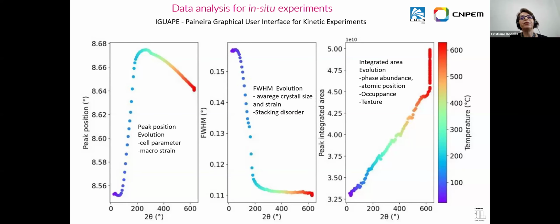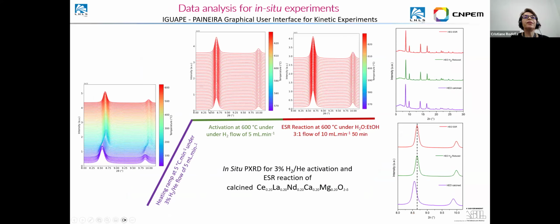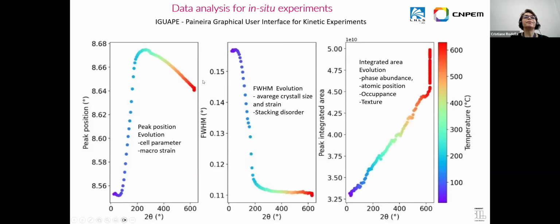What else do we offer? The user can take one of these peaks here and plot three things that can vary during the in situ experiment. One is the peak position, another is the peak width, and the third one is the integrated area, which will give more information about the structure. So with this, it's possible to infer the cell parameter variation or macro strain. With this result, how the crystal size or strain or disorders are working in the material. And here, the phase abundance, atomic positions, and texture and occupancy of the ions.